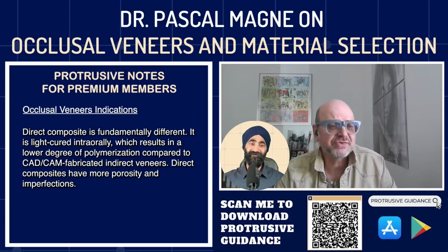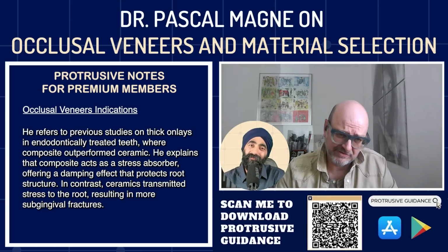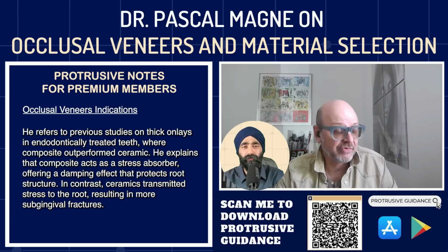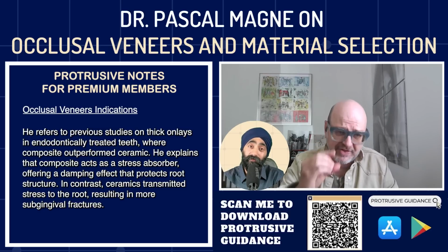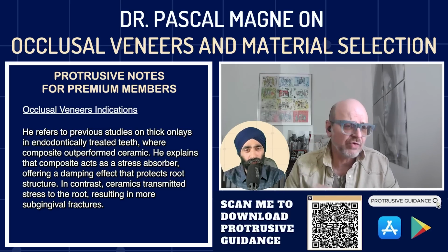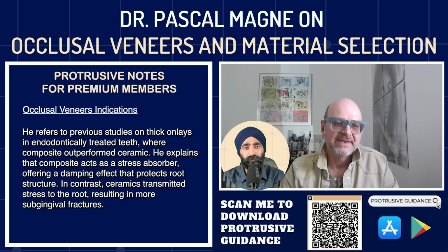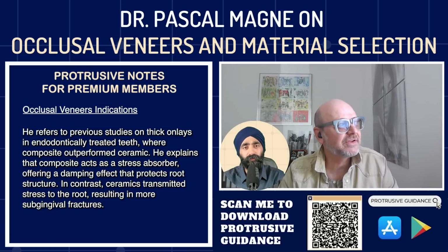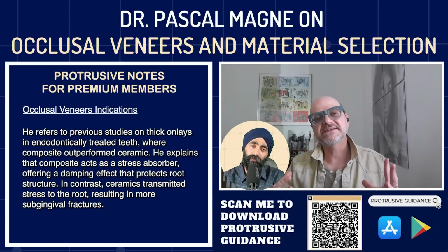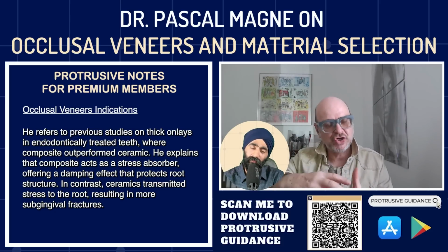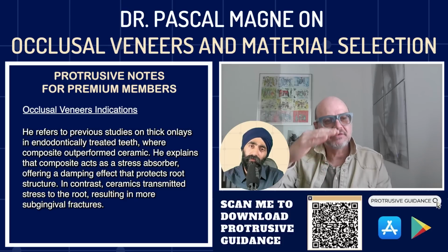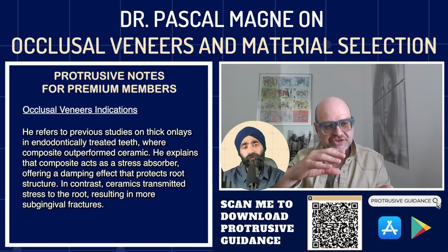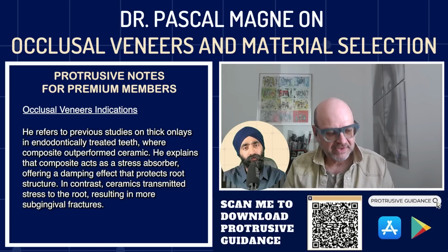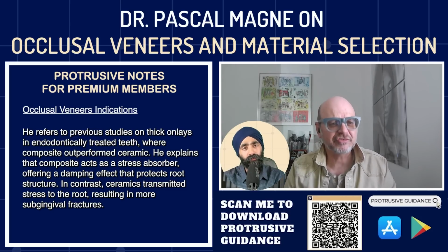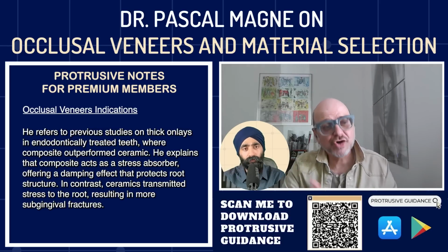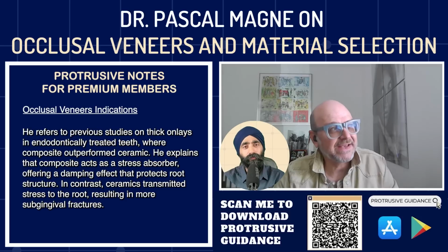And actually, we also tested that in the previous group of studies with endodontically treated teeth. So by the way, in those studies about thick onlays on endodontically treated teeth, the winner was very clearly the composite. And I like to say on an endodontically treated tooth, I like the idea of having the composite act as a stress absorber. And we had this effect of absorbing the occlusal load by deformation and protecting the root structure. So with the ceramic, we had more of a stress transfer straight into the root and more subgingival fractures also. So I like the idea of the composite.